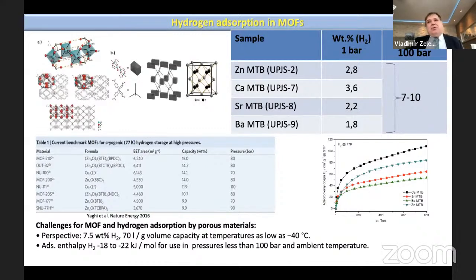At a high pressure up to 100 bars, it's about 7 to 10 weight percent. 100 bars is considered a safe solution for transportation. At present, we use, as I said, 700 bars. But for the future, this optimal limit is maximum 100 bars.